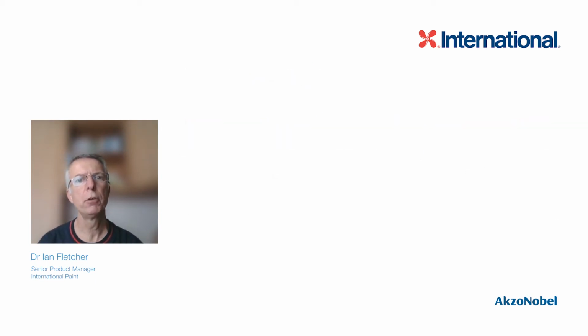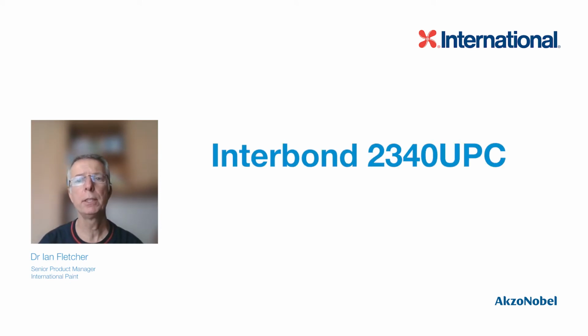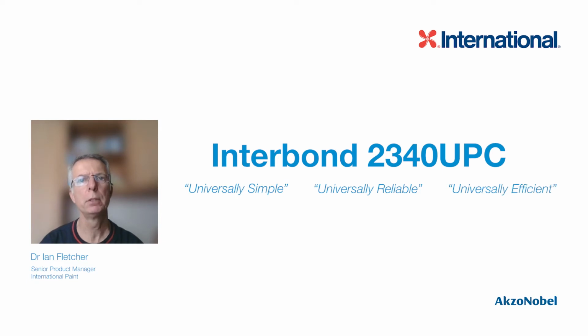As the vast majority of process piping operates below 230 degrees Celsius and CUI occurs below this temperature, I am now going to focus the rest of this webinar on Interbond 2340 UPC. Interbond 2340 UPC is an alkylated amine epoxy technology, which is a next generation epoxy phenolic, delivering corrosion and temperature resistance from -196 degrees Celsius to 230 degrees Celsius.